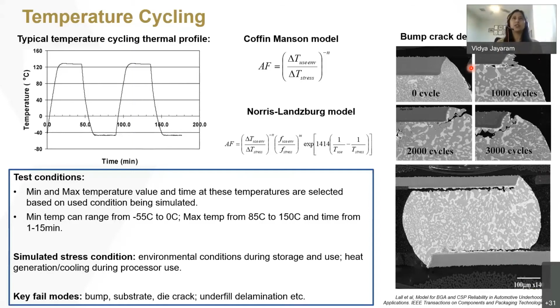Additionally, it can also be used to understand the thermal or thermomechanical stresses that are experienced by the processor itself when you're turning it on and off. So those are typically the kind of simulated stress conditions where you have the environmental conditions and also the heat generated by the processor itself. The key failure modes with this, as we discussed, are bump cracks, substrate cracks, die cracks, and underfill delamination, etc. In the image here on the top right, you can see the crack initiating and propagating over a period of time with increased number of thermal cycles.